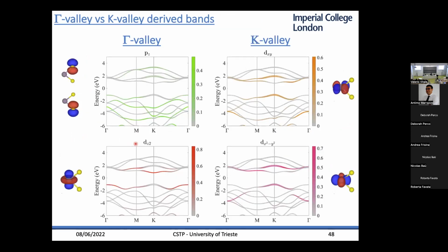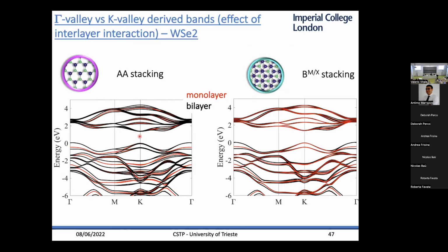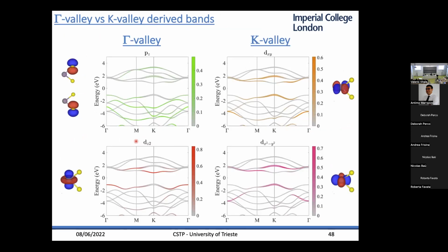So I just want to mention that which bands are on top, which states are on top, will affect the nature of the flat band in the Moiré system. And these bands have different contributions. Basically, the gamma valley has pz and dz squared character, as you can imagine. That's why it was important to introduce this in the tight binding. Whereas K valley states have high projection on d orbitals in the metal, in particular dxy and dx squared minus y squared.